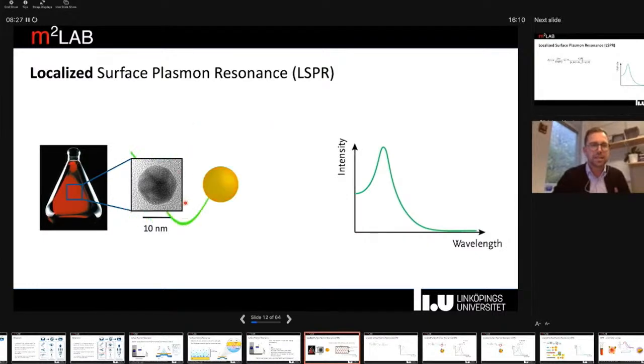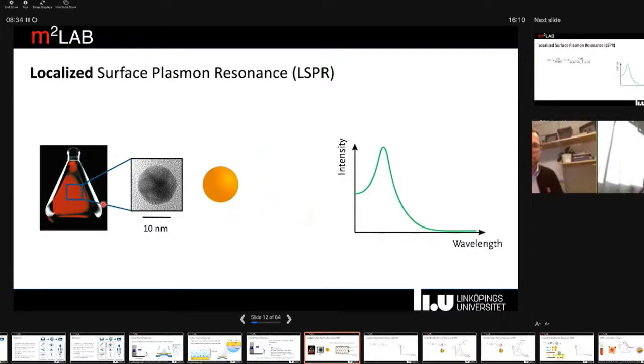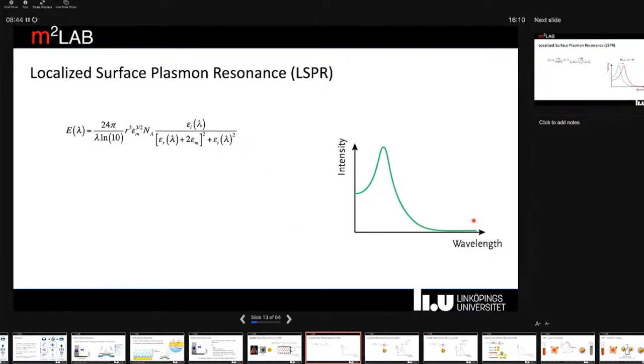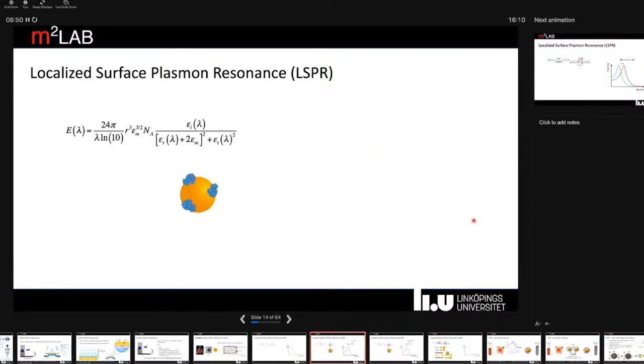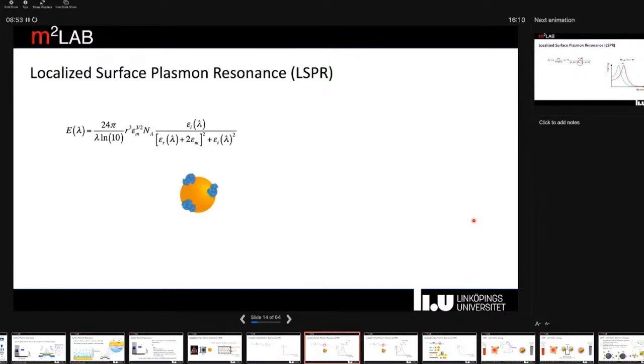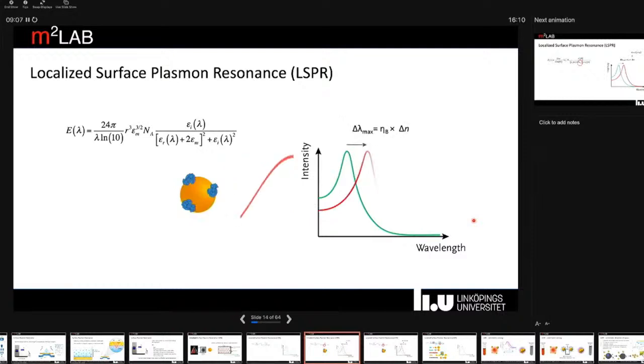For particles this size, this occurs in the green wavelength range, which makes the suspension of these particles look red. As you can see, there's literally no interaction with light here at this wavelength. The position and intensity of this LSPR band depends, just as in the case of SPR, on the dielectric properties of the vicinity of the particles. So if we, for example, immobilize or adsorb some sort of biomolecules on these particles, we'll obtain a change, or a redshift typically, in the plasmon band.